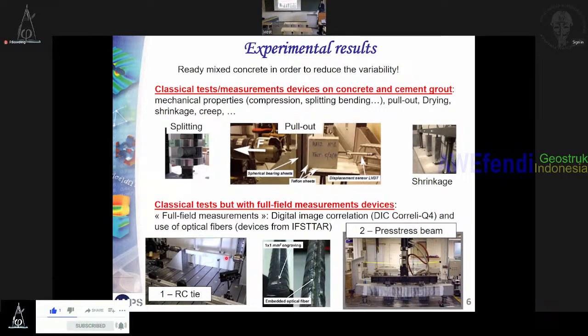And for full field measurements, we use two techniques. The first one is to use digital image correlation in order to have the field of displacement at the surface. But also we use optical fibers that have been glued at the surface of the rebar in order to have the evolution of the strain along the rebar.